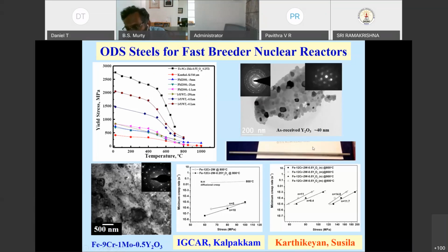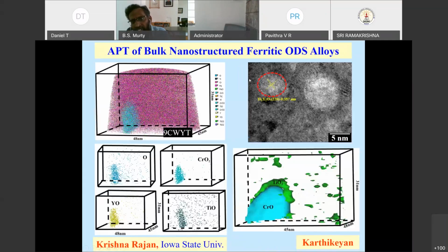And if you want to know what is happening, why, you can carefully see there are extremely small particles inside. You can go to a TEM and see these small particles. But the nature of these particles is very difficult to find out using a TEM. Whereas if you go to an atom probe, you will see a small particle, a 2 nanometer particle, which is that yttria nanoparticle. You wanted to know whether it is really pure yttria or something else is happening after I have embedded it into the steel.